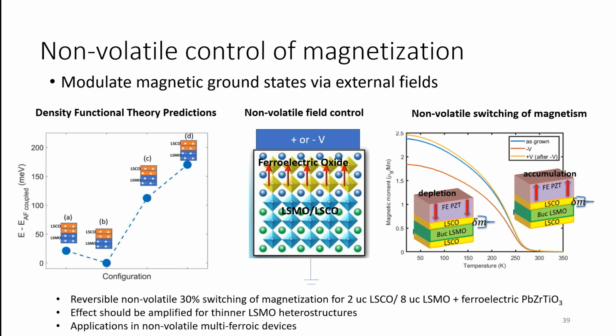So we've been starting some preliminary work on this, where we've put ferroelectrics on top, and we currently see a very small, well, it's a 30% modulation. It's not 100% as I would like, because we're using an 8-unit cell thick film. But we're working on trying to reduce the thickness of this LSMO down to the 2-unit cell thick level so that we can actually get this 100% modulation in the magnetism in this system.